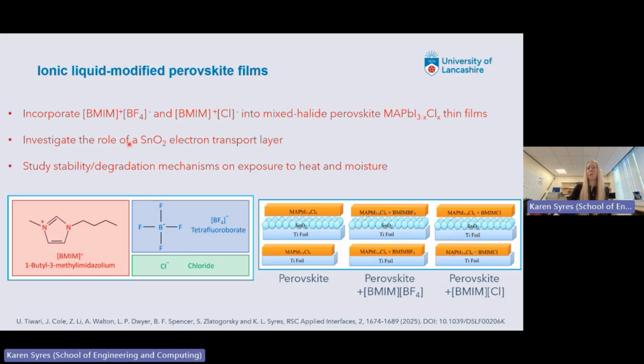And then we looked at what happens when we deposit the perovskite ionic liquid mixture onto a tin oxide layer. We were basically just trying to study the stability of them and how these things degrade when we expose them to heat and moisture. So we heated the sample up and we also exposed it to water vapor.